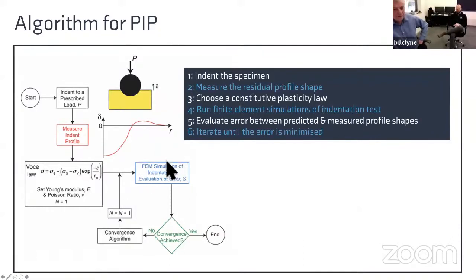So you carry out an FEM simulation of the test. You look at the predicted profile, you compare it with the experimental one, and you evaluate the difference between them, the error, this S parameter. And the better the fit, the smaller the value of S. So you decide whether you've converged sufficiently. If not, you repeatedly carry out the FEM simulation with altered values of these plasticity parameters until you get the best fit, and then that's given you the plasticity law. From that point, you can do all sorts of things, simulating other situations, etc.